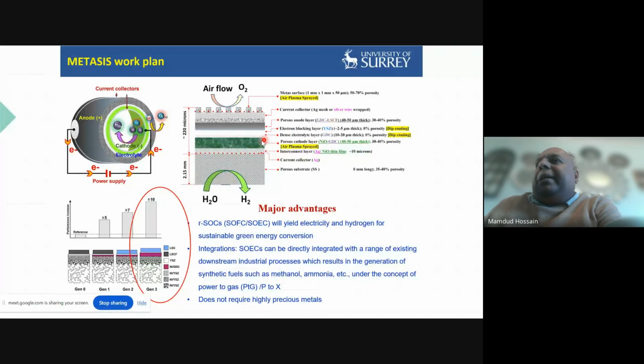Then we have nickel oxide and GDC material with a porosity of 30 to 40%. Then we create a dense electrolyte made of GDC and YSZ, in two or multiple layers. Then we have a porous cathode with GDC and LSCF, porosity of 30 to 40%, thickness 40 to 50 micron. Our advantage is that initially this type of structure used to be 400 to 500 micron, because that provided the support.